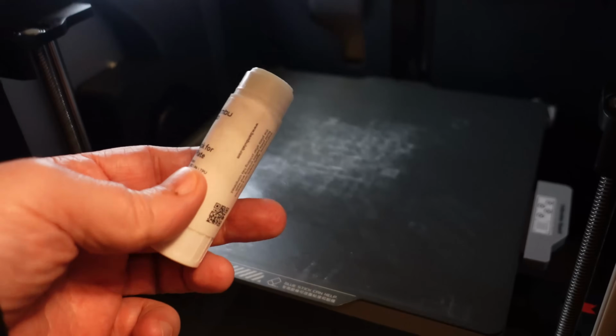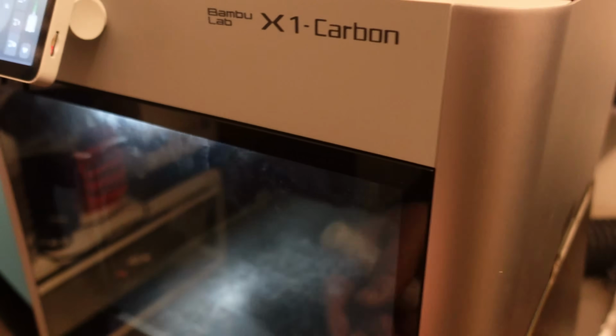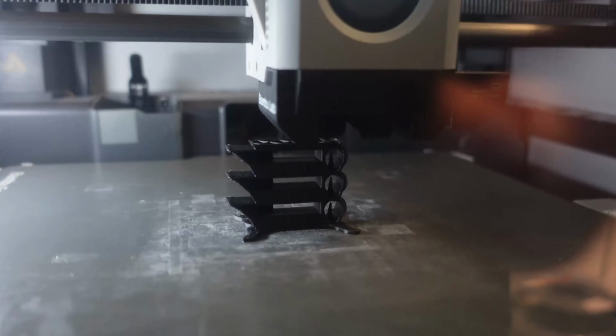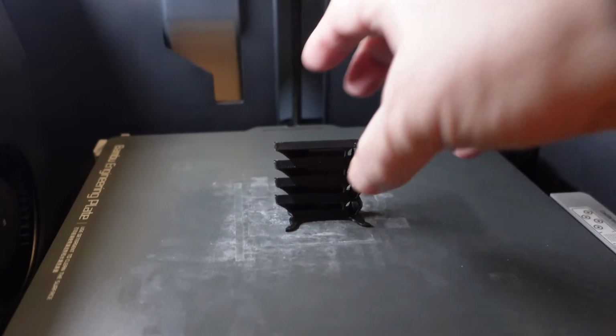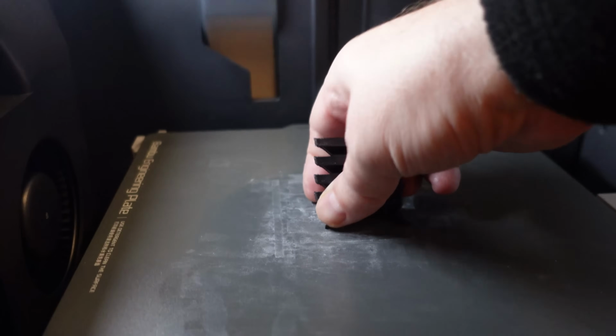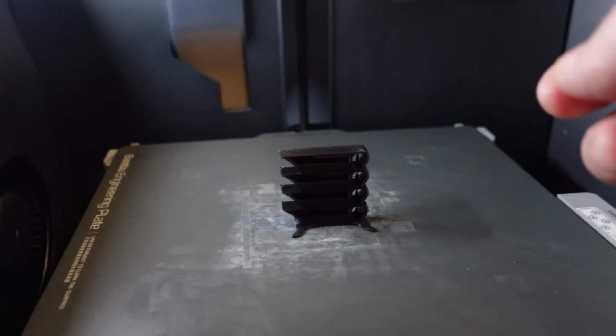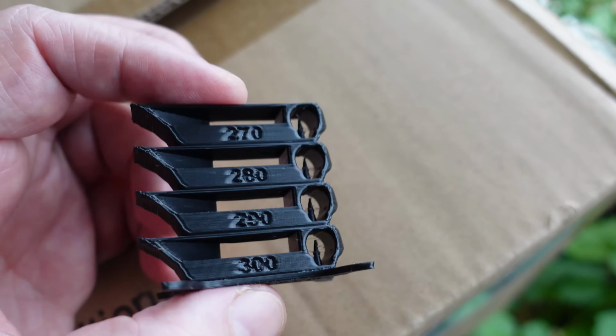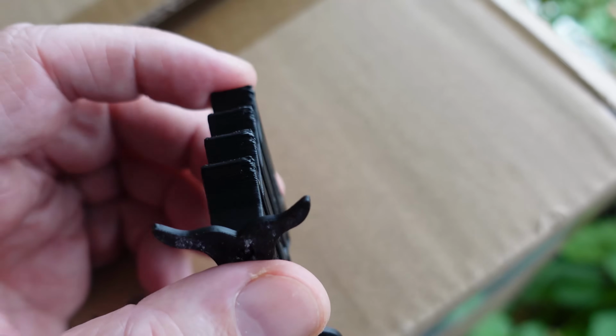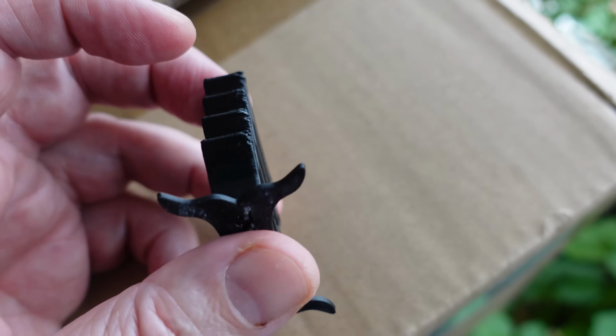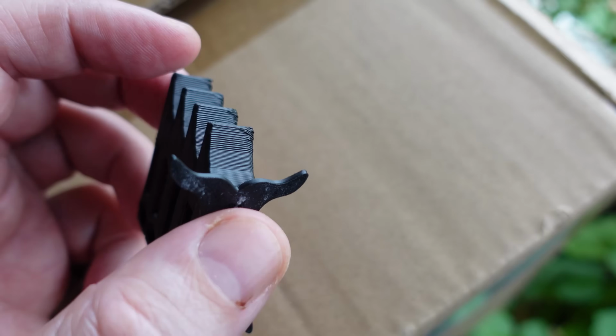Engineering plate with some glue on it. The start is okay, it sticks well to this engineering plate. And this is the first element at 270 degrees Celsius. Bed adhesion check. It's good. Looks nice on almost any element. I can see a little bit more stringing here at the higher temperatures. And I can also see a little bit more melted seam lines on the overhangs at the higher temperature.